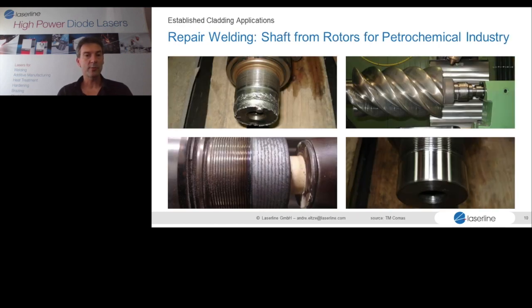I mentioned the examples of repair welding, also very well established. This is from a Spanish customer. You can see on the upper left corner the worn out shaft from some rotor for petrochemical industry. On the lower left side, you can see the clad surface. On the upper right corner, you see the process. And on the lower right corner, you can see the finished part as it comes out from the machine after machining of the surface. In many cases, the repaired part is better than the original part because you can use more suitable, maybe more wear-resistant powders in the process.